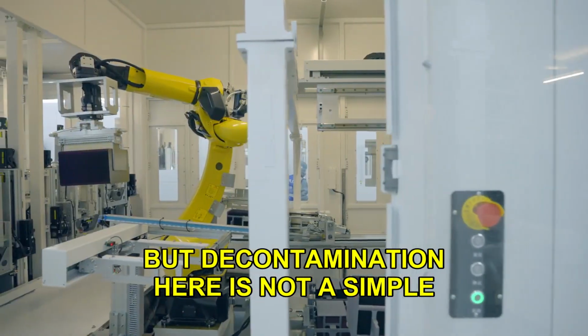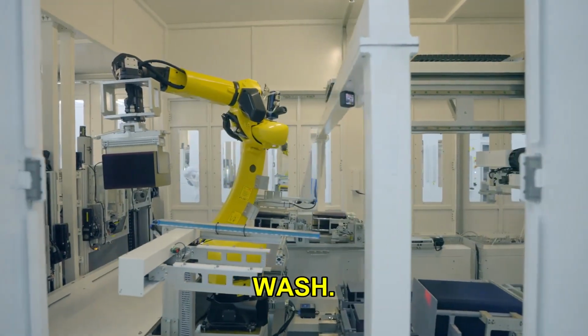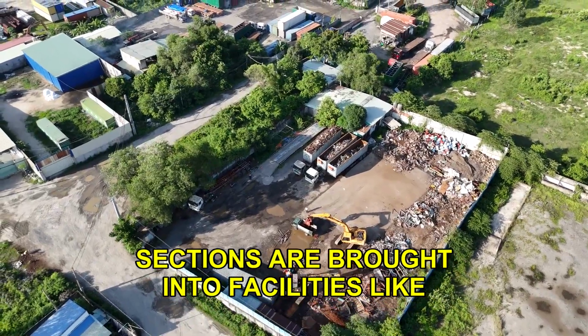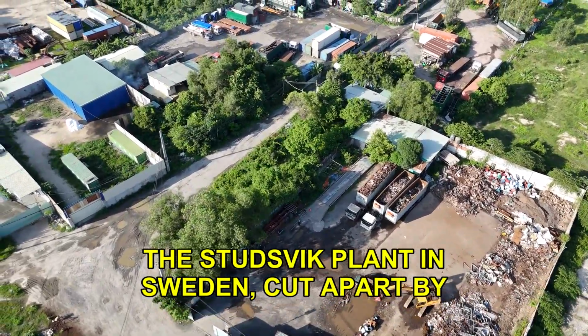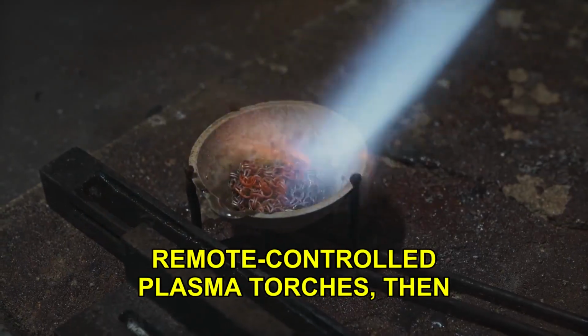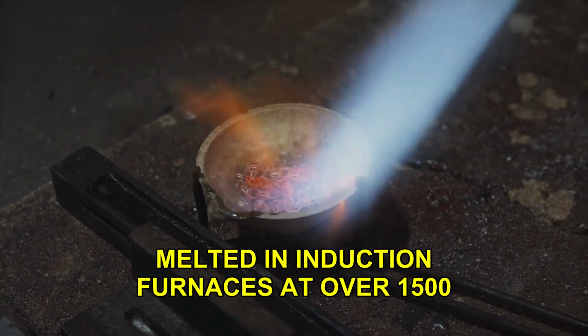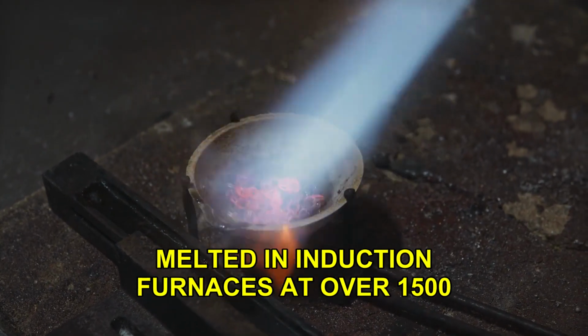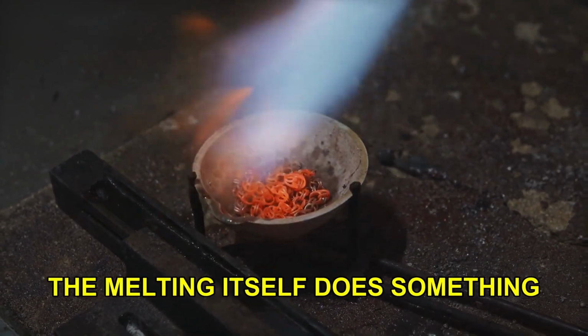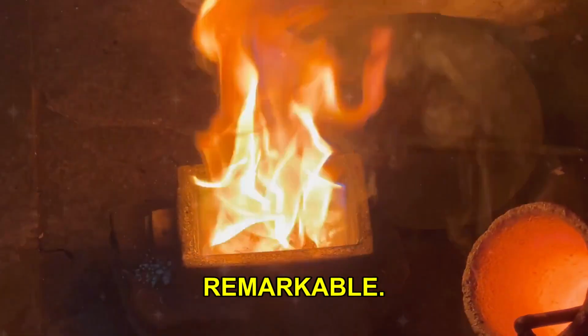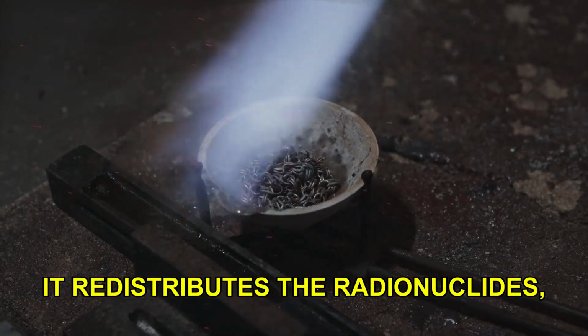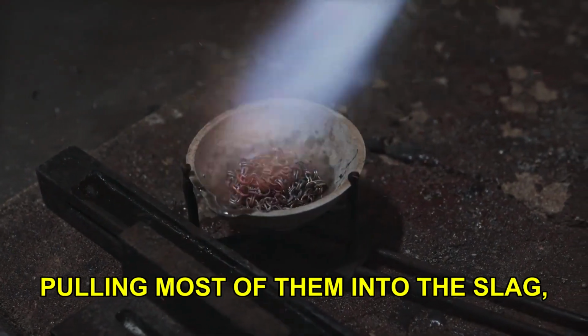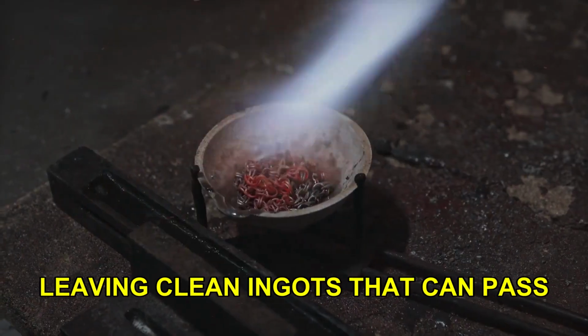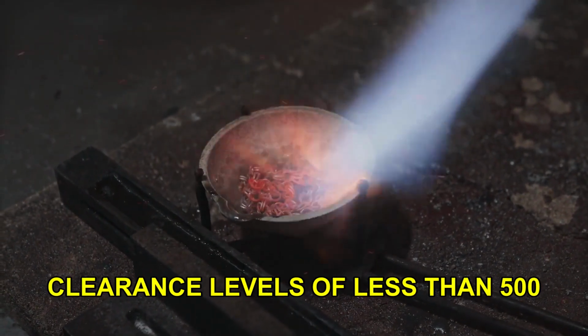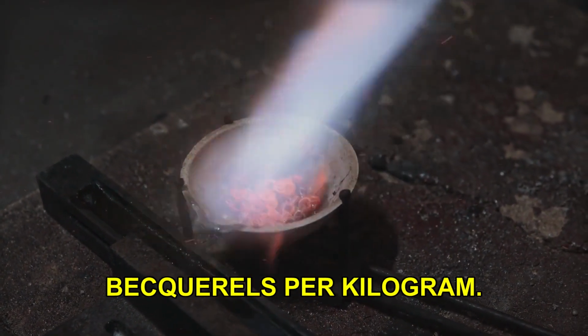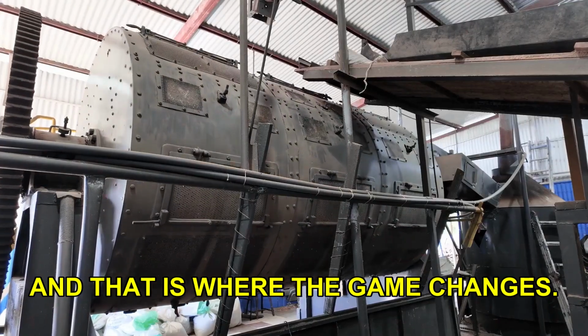But decontamination here is not a simple wash. Sections are brought into facilities like the Studsvik plant in Sweden, cut apart by remote-controlled plasma torches, then melted in induction furnaces at over 1,500 degrees. The melting itself does something remarkable. It redistributes the radionuclides, pulling most of them into the slag, leaving clean ingots that can pass clearance levels of less than 500 becquerels per kilogram. And that is where the game changes.